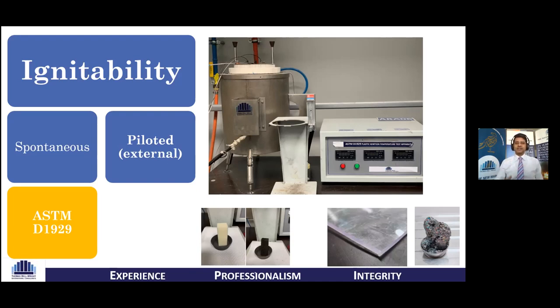So what the test method does is that we take the samples, we prepare them, and we maintain a constant temperature in the hot air furnace. And we could probably start at 300 or 400 degrees, and we keep on increasing the temperature, and we try and figure out the exact temperature at which the product or the material will spontaneously catch fire. This is a test method which is mainly used for plastics or even materials which would contain plastics.